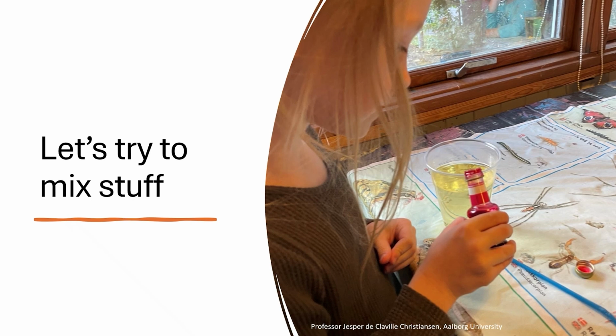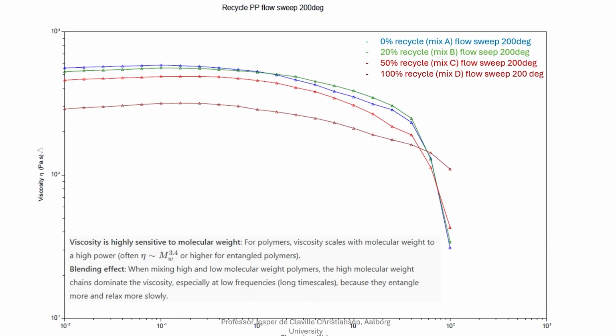If we try to mix stuff, this is my granddaughter mixing, and here I'm mixing, then we get these results. So you have shear rate on the first axis and you have viscosity on the second axis. And in this case, it's no longer the complex viscosity from oscillatory measurements, it's real shear rate measured in rotation. And what we can see is the virgin material, the blue in the top, and we can see the 100% recycled mix in the lowest of the four graphs. So adding up to 50% recycled do change the viscosity, however, not as significantly as 100% recycled material. The reason for this is because the viscosity scales with the molecular weight to the power 3.4. So having the large molecular weight fractions significantly alter the viscosity of the sample.